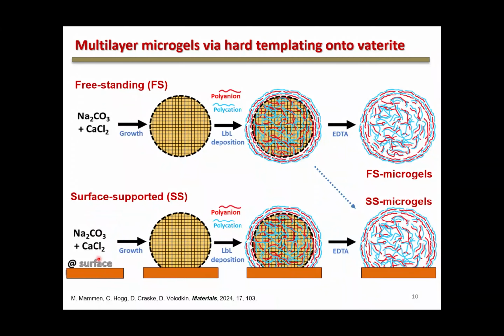And what we found is that everything, like in the typical procedure, you can do in the presence of the surface, and then all steps will be done using the surface. All particles here will adhere to the surface. It's very easy to work with them. And finally, you will have not freestanding, but surface supported microgels. They stick to the surface.